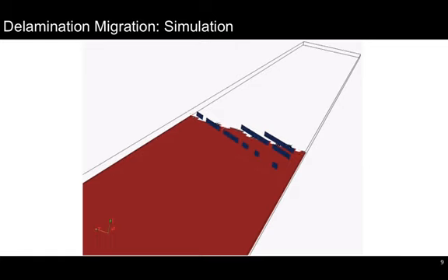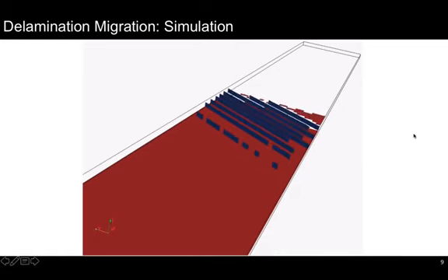You can see the delamination first started on the lower interface, and then you can see all these attempts by the matrix cracks to kink up the delamination, but eventually it happens at a later stage than the first appearance of matrix crack, and then the migration is clearly caused by, in this case, 3 different matrix cracks.